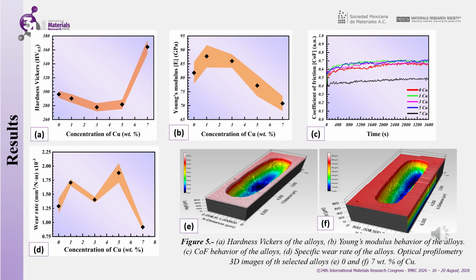Figure 5b presents a variation of Young's modulus, E, with respect to the concentration of copper. The reference alloy containing no copper has a modulus of approximately 82 gigapascals. When 1% copper is added, an increase to approximately 88 gigapascals is observed, indicating greater elastic stiffness of the material at this concentration. However, for higher concentrations, a downward trend is observed. The modulus remains close to 86 gigapascals for 3% copper, decreases to approximately 77 gigapascals at 5% copper, and reaches around 71 gigapascals for 7% copper. This behavior indicates that an increase in copper does not result in a continuous increase in stiffness. Rather, it modifies the elastic response in accordance with the composition, and possibly with changes in the structure and the phases present.